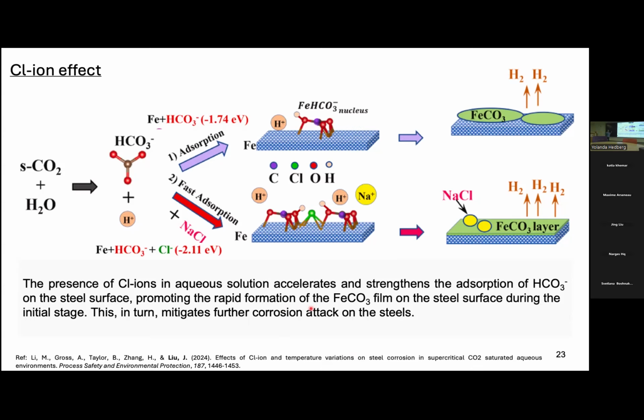So why is sodium chloride solution less corrosive compared to DI water? When you have chloride, the iron carbonate absorption is much easier compared to when there is no chloride. So they can quickly form the layer. So it all goes back to how we can explain the corrosion rate. It can be explained by the quality of the corrosion product layer. So that's a chloride effect.